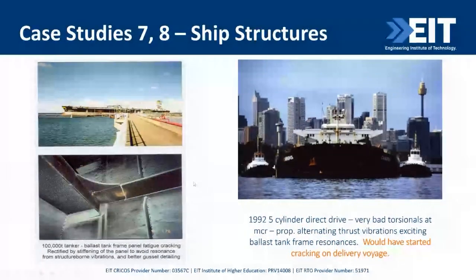The second ship was a large tanker back in the early 90s, cracking on a ballast tank frame, a panel, a lower panel, which still an open frame higher up, you'll see, cracking across the longitudinals to the gussets, longitudinals going across the cross stiffeners to the frame. 5-cylinder direct drive diesel, and we thought that was similar buckling, low cycle buckling, due to the change in load and unload. That was wrong.